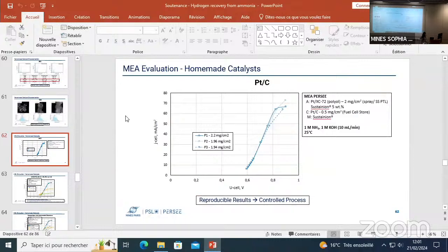Yeah, that's true. It can give you a lot of information about, of course, the OH conductivity of your membrane, but also how all your materials are compressed into the cell. And so this also helps to see every time that you are doing another measurement that you are correctly in the right conditions, that allows you to compare all the results. And so that's one type of correction that one can do to a polarization curve.